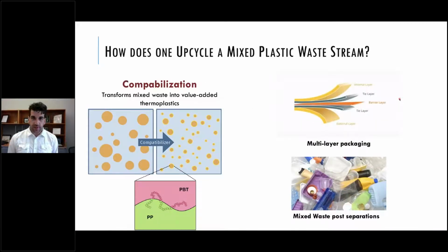Another example of upcycling that I'm interested in is compatibilization. So compatibilization is when you take a mixed waste stream, and typically these mixed waste streams, right, on a kind of micron scale are composed of these two plastics that don't mix with each other. So usually one plastic forms a continuous phase, the other plastic forms these large droplets. And if you just take this material and look at its properties, it's usually very brittle. And it's brittle because, right, you have these huge droplets of one plastic in another. There's no interfacial adhesion between those two plastics. So when you start to apply a strain to that material, it breaks really quickly at that interface and just shatters.